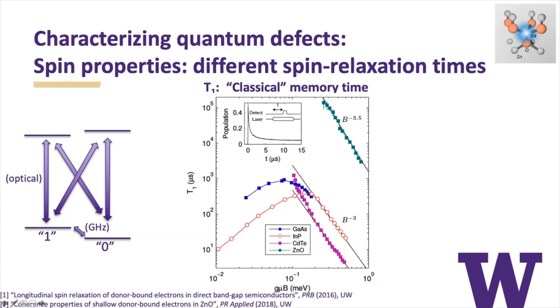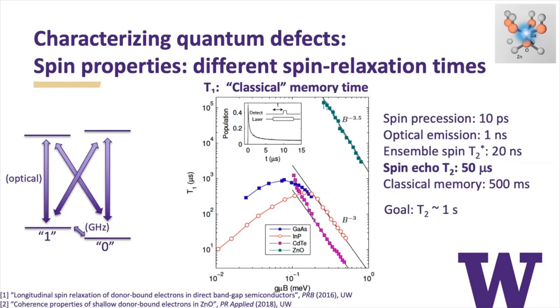But we take these measurements as a function of magnetic field to understand the mechanism for relaxation. And in this case, these earlier measurements really said go to low spin orbit coupling material. So we went to zinc oxide and got an increase of 3 orders of magnitude. Okay. And then a lot of people say, all right, well, what is your goal? How long do you want T2 or this quantum memory time to be for defects or network applications?